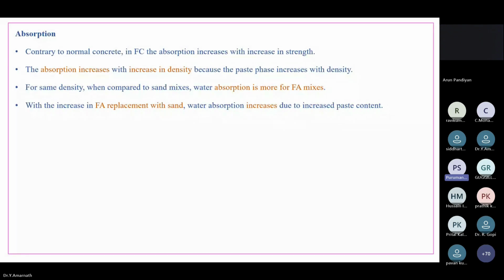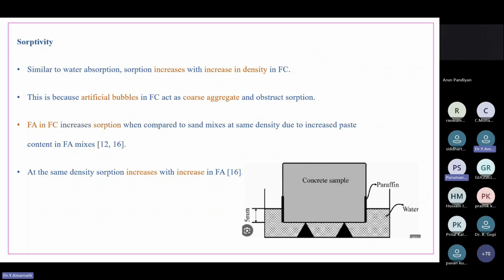Absorption. Similar to water absorption, sorption increases with increase in density. As density increases, absorption also increases. This is because artificial bubbles in foam concrete act as coarse aggregate and obstruct. As density decreases, the artificial bubbles increase, and absorption decreases when compared to solid.